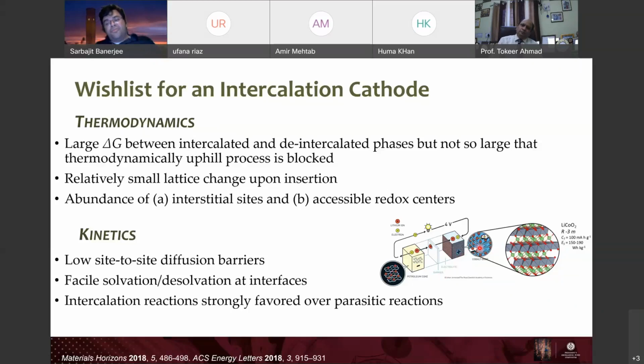And then the next problem we have to solve, lots of interfaces, either solution phase interfaces or solid state interfaces in the case of all solid state batteries. But for example, an interface here between the electrolyte and the cathode, or electrolyte and the anode. And at that interface, right, the lithium ion, as long as it's in the electrolyte, is coordinated by some sort of counter ion, right? There's some sort of counter ion with it. It's got to leave that behind and enter inside the solid. So that's these desolvation reactions that are required.